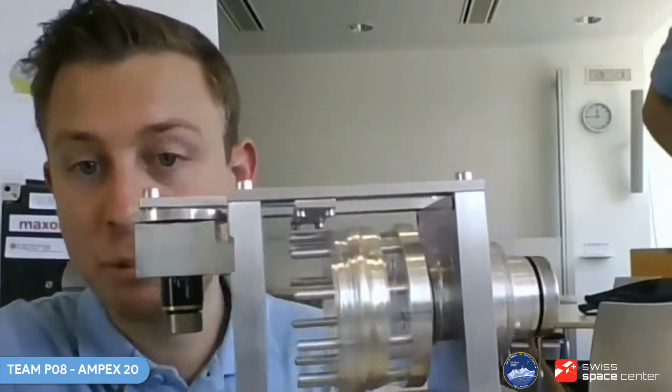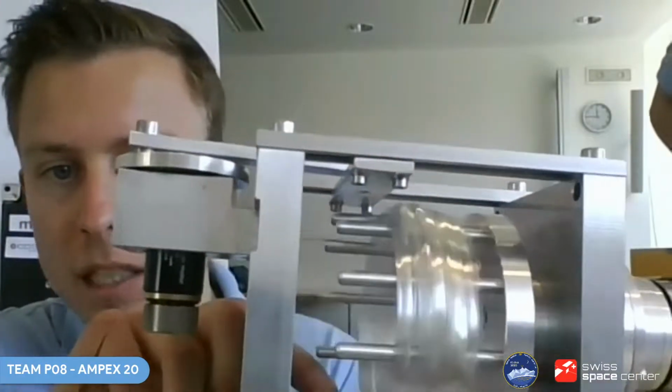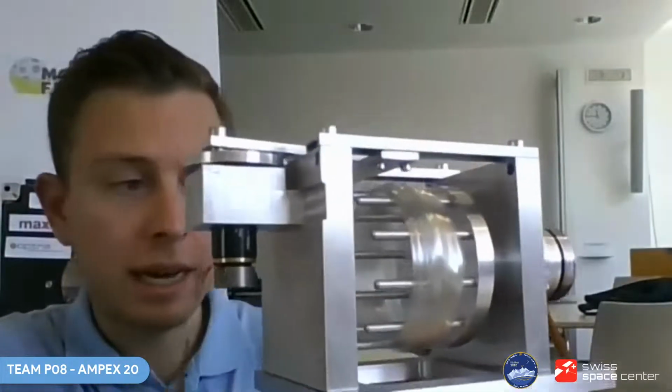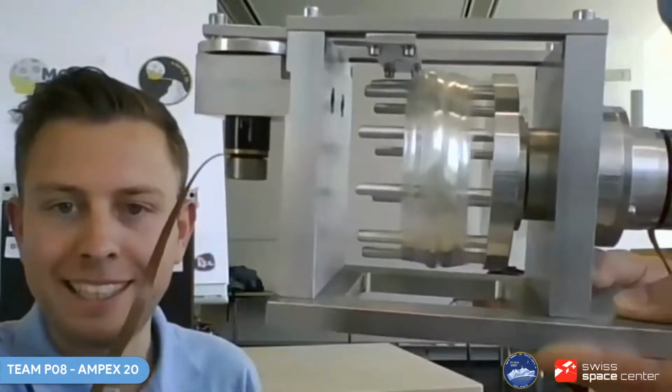I'm actually really glad that you asked this question, because I've just run down from the spinning plant and disconnected the winding system. So you can here actually see the fibers that we just spun in the live demonstration. As we said, this is just E-glass, so basically the glass fibers that you use in internet cables and so on. And we actually can produce a revolution speed that's high enough to get the same velocities as in the industry. So we can actually produce fibers that are 6 micrometers in diameter, which is basically the exact standard that the whole world uses. So you see, this is actually working, and we did it.